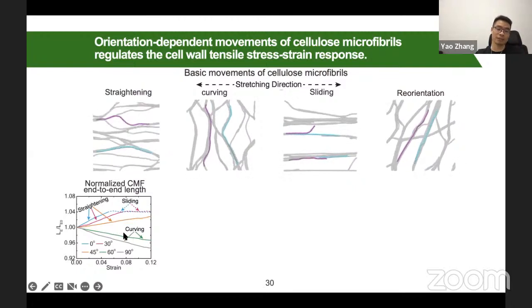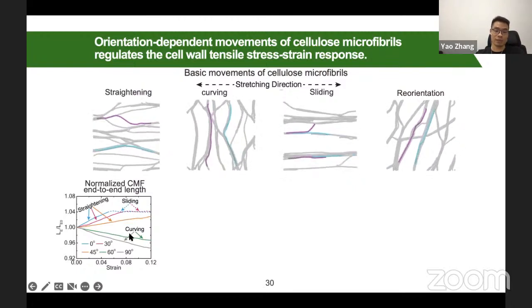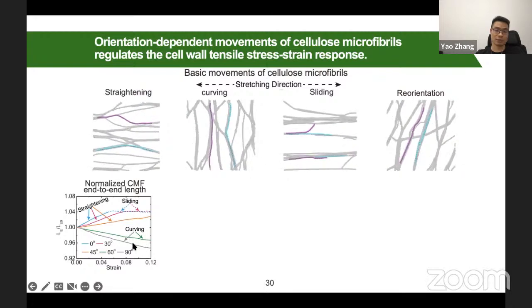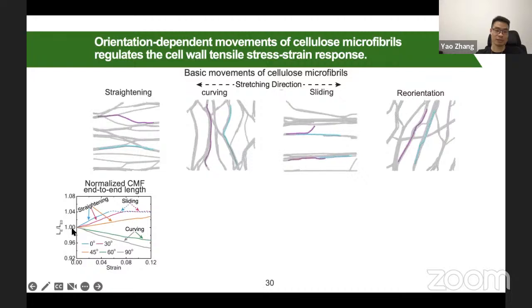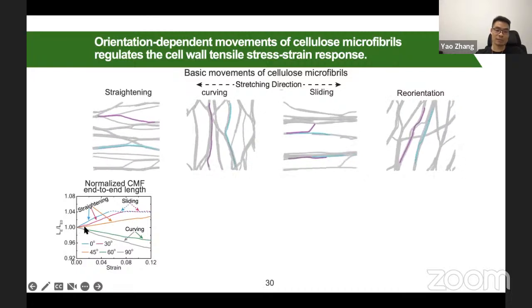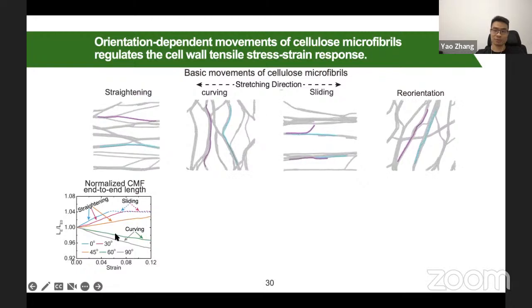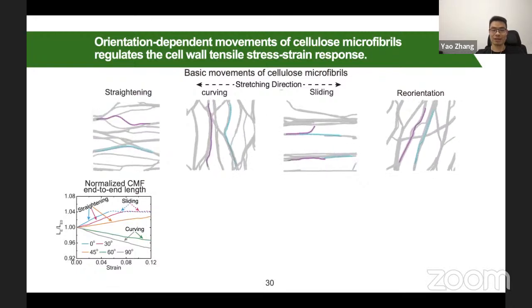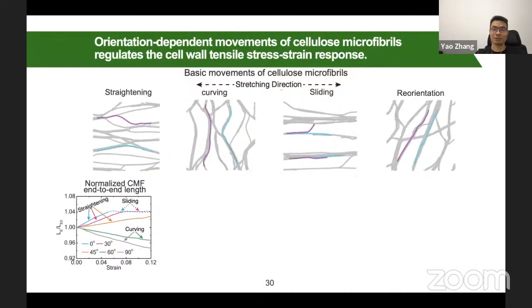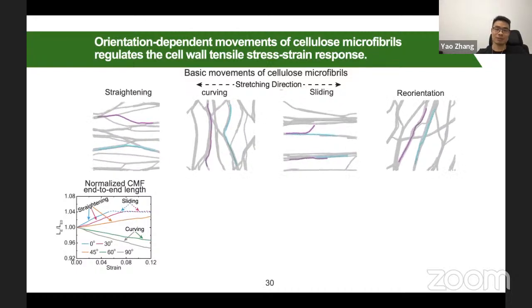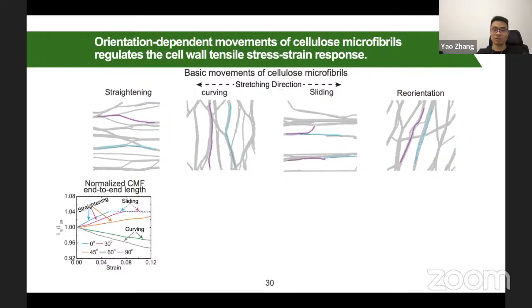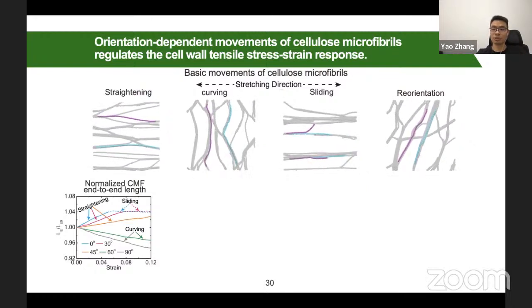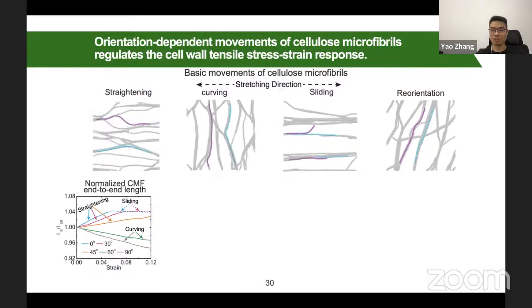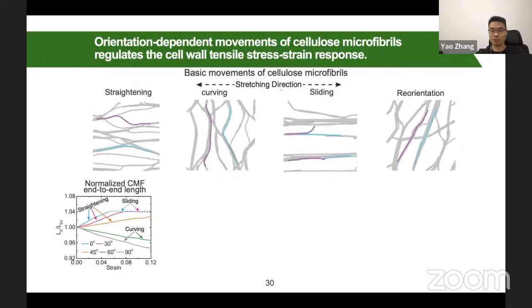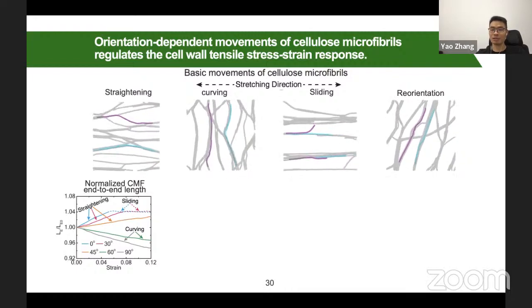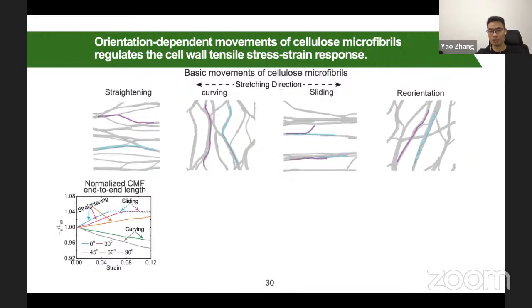Also, if you look at the two layers, which are the green line and the gray line, you can see that the end-to-end length keeps decreasing. That's because it's more like a Poisson's ratio: when you stretch your layer, the cellulose orientation is almost perpendicular to your strain direction. So it will be compressed along the direction which is perpendicular to the stretching direction.